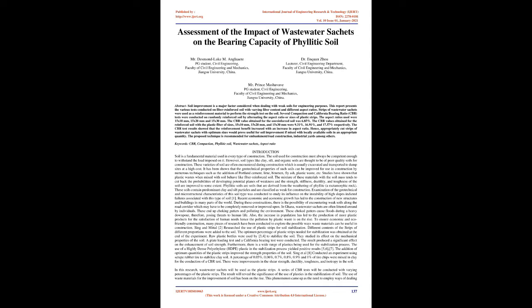Strips of wastewater sachets were used as a reinforcement material to perform the strength test on the soil. Several compaction and California bearing ratio (CBR) tests were conducted on randomly reinforced soil by alternating the aspect ratio or sizes of plastic strips. The aspect ratios used were 15x10 mm, 15x20 mm, and 15x30 mm. The CBR value obtained for the unreinforced soil was 6.85%.